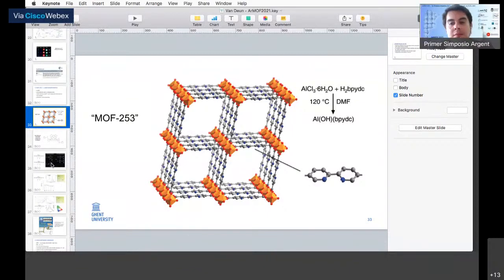No, in that way, I don't really know any alternative, because what can you do to make it porous? It's remove the molecules and then it will collapse probably. So I think you really have to build a completely different MOF in which you have to take into account, of course, that the coordination number of lanthanides is always higher than in transition metals. So you typically aim at 8 or 9 donor atoms around the lanthanides, and it's difficult.